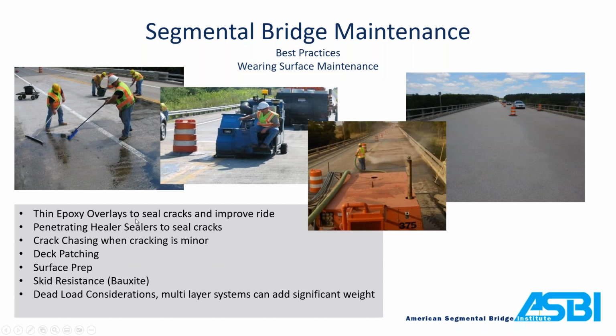Thin epoxy overlays, again, multiple ways to put these on. I've seen crews that do it with the bucket system. I've seen automated trucks that are mixing this thing and spreading it all in one shot. It really doesn't matter as long as it's getting the job done. Thin epoxy overlays will bridge the crack and sit on top and have a heavier aggregate. Typically, they're 2-coat systems. A penetrating healer sealer will penetrate the crack, and then it just has a sand aggregate on top just to take the sheen off. So they're a little bit different.